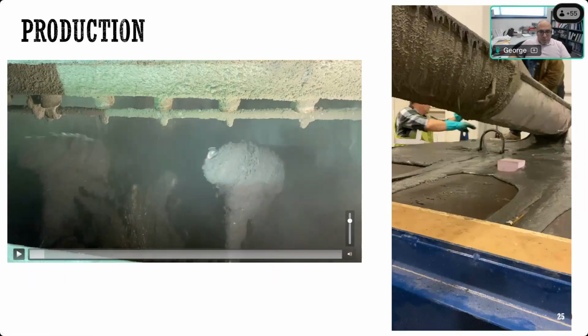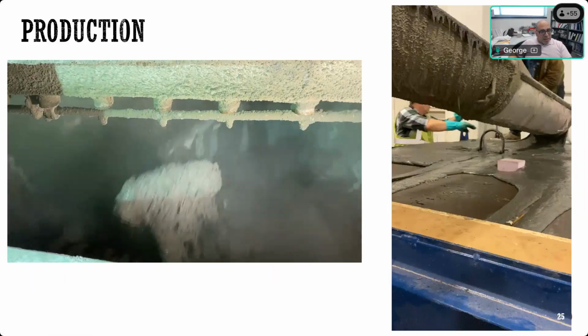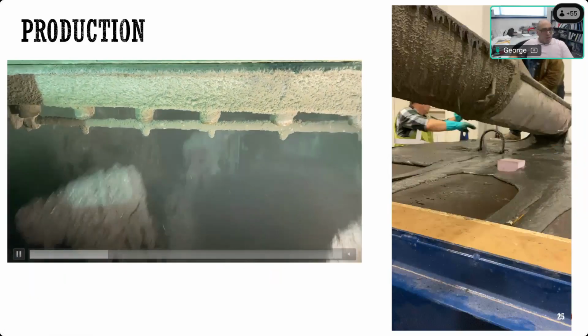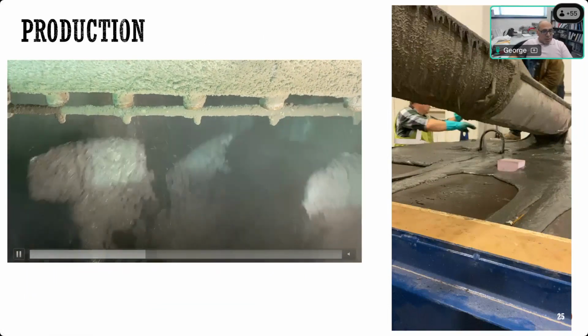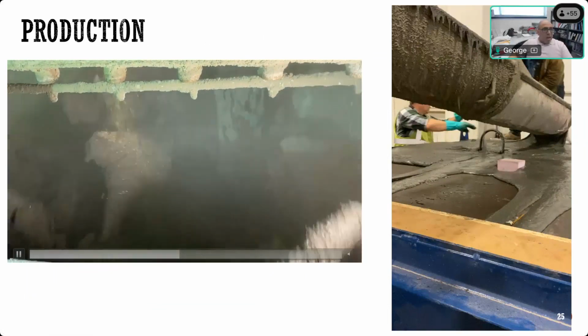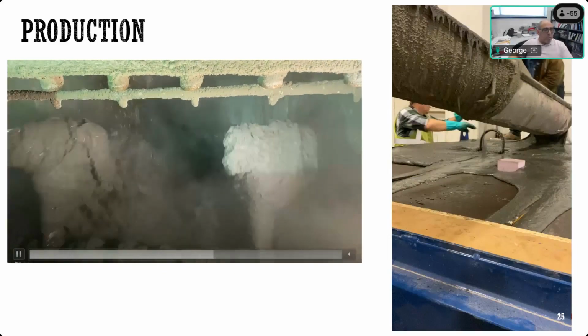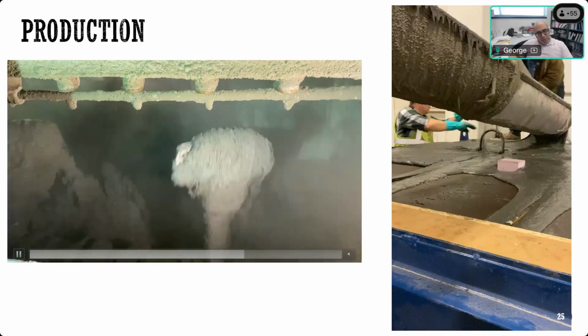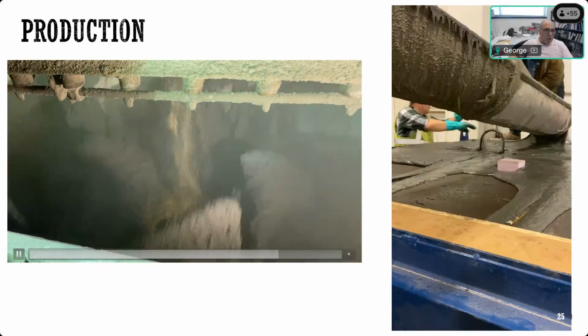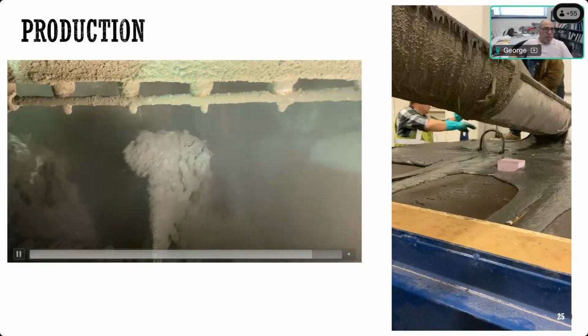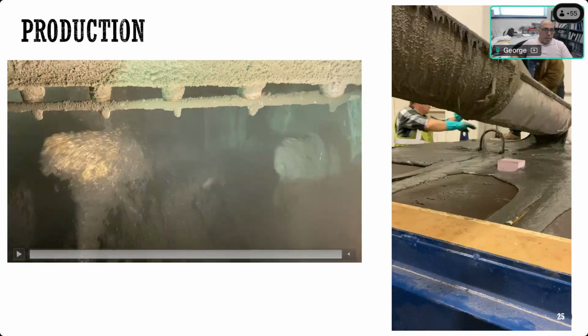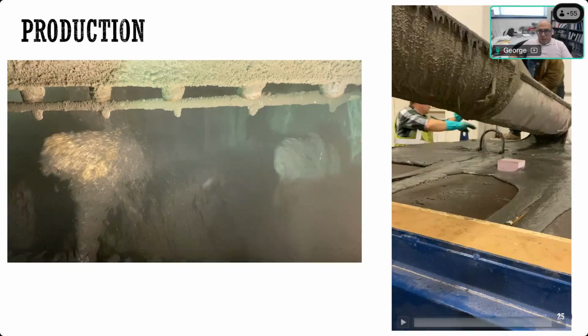Just to show you some pictures also. This is the mixing in the precast plant, and you can see the fibers were added after the mix became flowable. That's how you do it. You mix it until it becomes flowable, and then you add the fibers to the concrete, so you get them well distributed, and the concrete flows pretty well.